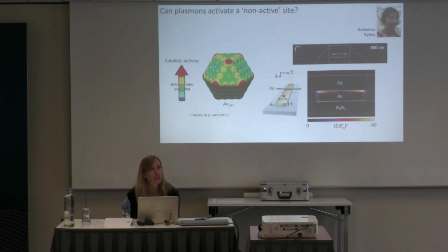No, it's a great question, and our lab hasn't done it, but there have been labs that have just used LEDs or solar-driven LEDs. And just to put things in perspective, if you've ever seen a stained glass window or a rose window, that does not need to be illuminated with a laser to see the colors, right? Basically those stained glass windows are just metal nanoparticles doped into glass, and the resonance of those metal nanoparticles is what's giving rise to the color you see. So it's very easy to excite resonances in metal nanoparticles. And we just use a laser because it's a more convenient source to make sure we have that wavelength tunability.